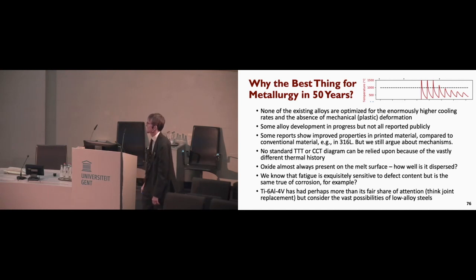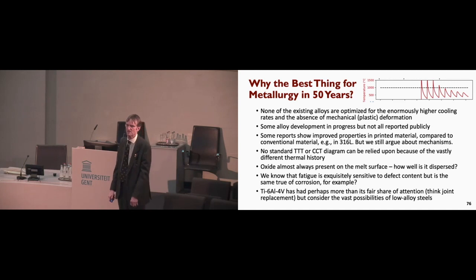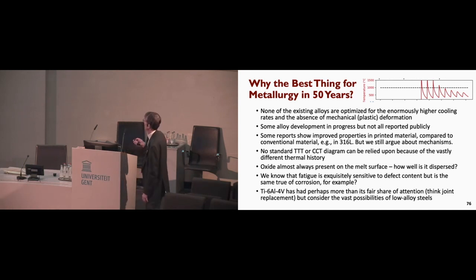Fatigue is exquisitely sensitive to defects because it's such an extreme value problem. And is that true of corrosion as well? Well, that's something still to be answered. Ti-6-4 has had a lot of attention, really more than its fair share. So we do know a few things about how that particular alloy behaves. But consider all of the different low alloy steels. I mean, there's this huge range of possible compositions and learning how to work with those. And that's just one particular alloy system, if you like. So this typical thermal history opens up multiple new chapters, I would assert.